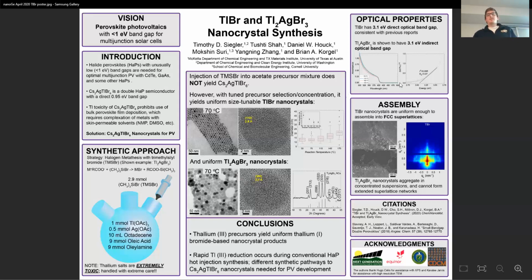The optical properties of these materials show that they're not very well suited for direct photovoltaic applications, as they both have 3.1 eV band gaps. However, they're very high quality nanocrystals, with thallium bromide nanocrystals even forming extended FCC superlattice networks that have very strong small angle X-ray scattering diffraction patterns. Therefore, we hypothesize these materials might find good application as radiation detectors or radiation scintillating materials.